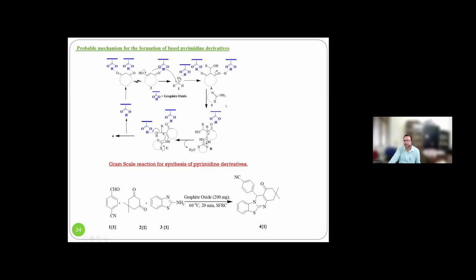Now, this is the mechanism here. Again, the acid part of the graphene activates the carbonyl carbon, and then intramolecular addition and cyclization gives the pyrimidine derivative. Again, we did the gram scale synthesis, and it gives good results also.